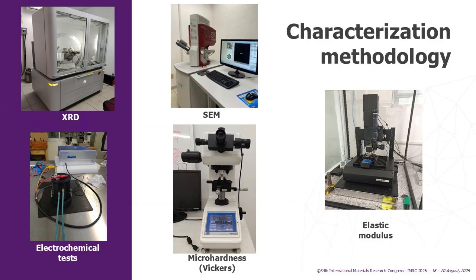The samples were characterized following metallographic preparation, employing silicon carbide sandpaper for roughing, and alumina of 3, 1, and 0.05 micrometers, in addition to a 0.02 micrometers silica solution for polishing until a mirror finish was achieved.